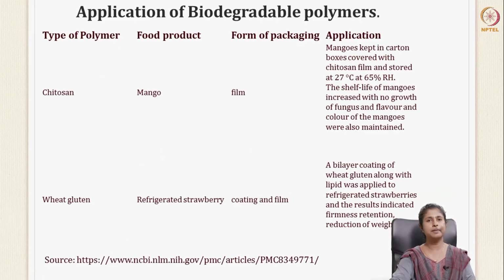Now coming to the last part, which is the application. I have mentioned just 5 applications from research in the papers mentioned here. One is using chitosan. They used mango and made a film out of that. These mangoes were kept in carton boxes covered with these chitosan films, and they were stored at 27 degrees centigrade, 65% relative humidity. The shelf life of the mangoes increased with no growth of fungus, and the flavor and color of the mangoes were also maintained. That gave positive results.